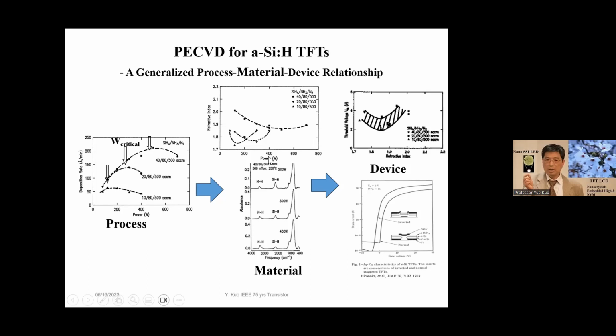And those material properties can further be correlated to TFT device performance. This shows that no matter what your process condition is, eventually there are optimized material properties for the best TFT transistor performance. In this case, the refractive index of the silicon nitride gate dielectric is between 1.85 and 1.9. That gives the best threshold voltage and the most reliable device.